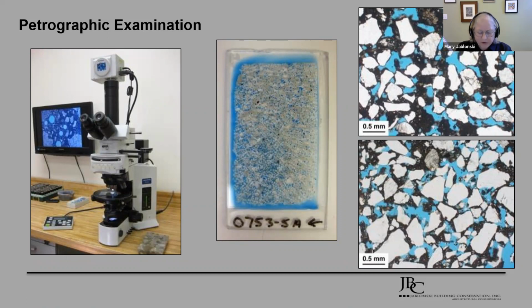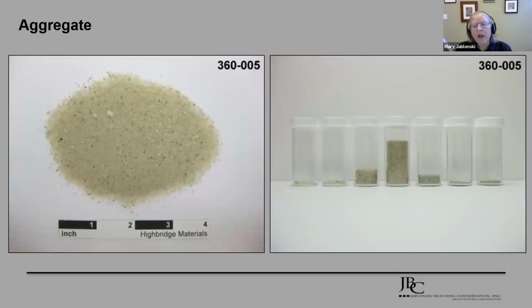But petrographic analysis can be used to identify chemical and physical elements of the concrete, including the nature of deterioration, the identification of aggregate strength, mixture proportion estimates such as water and cement ratio, aggregate size and distribution. And we actually found some really fascinating findings from this. This was the aggregate. Now, a number of you probably are quite conversant with aggregate in Portland cement or in cast stone. This is extremely fine aggregate, not what you would ever think would be found with concrete.